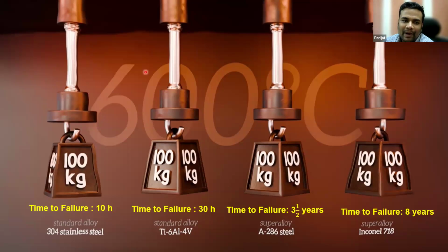Okay. Now these four bars are experiencing a load. We put a sufficient load of around 100 kg so that each bar experiences an internal stress of 300 megapascal. At the same time, we are increasing the temperature up to 600 degrees centigrade. If you run this experiment, you see that the standard stainless steel alloy will fail, will break apart at around 10 hours. And the titanium 6 aluminum 4 vanadium alloy, that means 6% aluminum, 4% vanadium, will fail in around 30 hours. If you take the iron-based superalloy, the time to failure is 3.5 years. If you put this constant 600 degree temperature and constant load, it will take 3.5 years to fracture, which is a phenomenon known as creep.